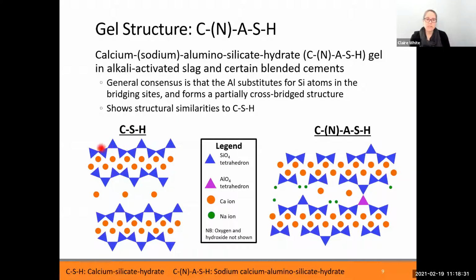C-S-H gel has finite length silica chains. They're not infinite as shown here, but they are finite. Over here with the NASH gel, they are different. People have seen that from NMR, and we're going to talk about that today as well. And then the real question is, how does sodium impact the C-S-H gel? Does it just substitute for a calcium and therefore it's happy to sit there, or, you know, 2 sodiums for a calcium? Or is there other stuff going on when sodium's incorporated into the structure?